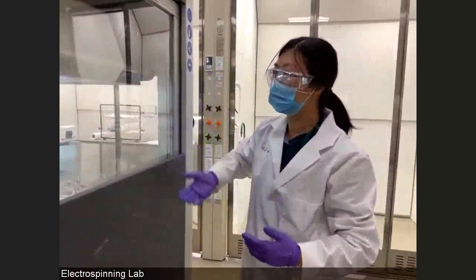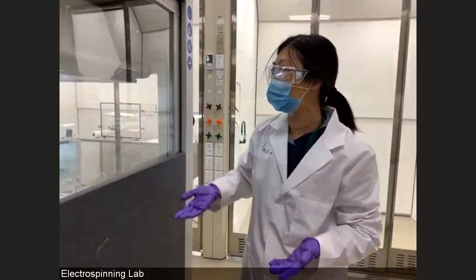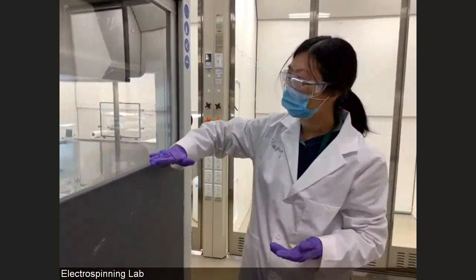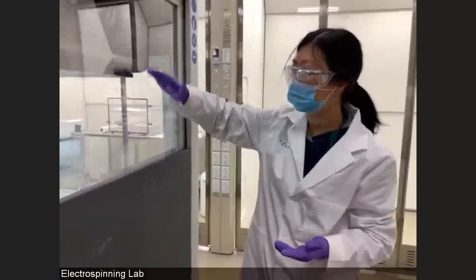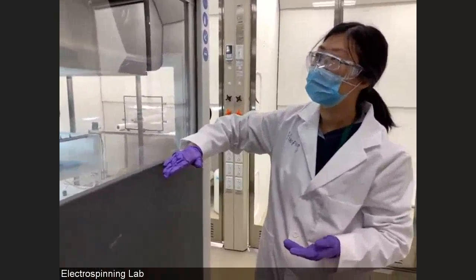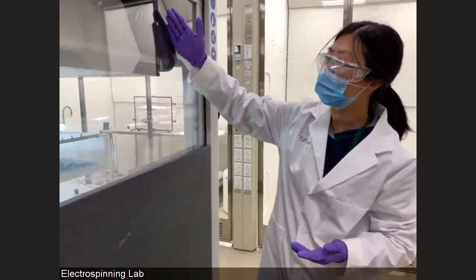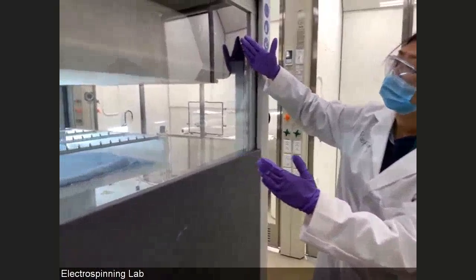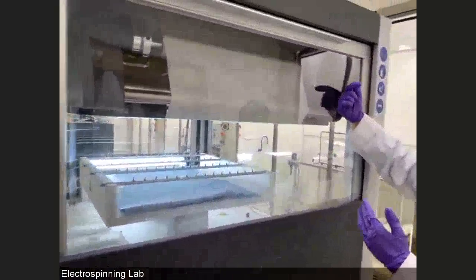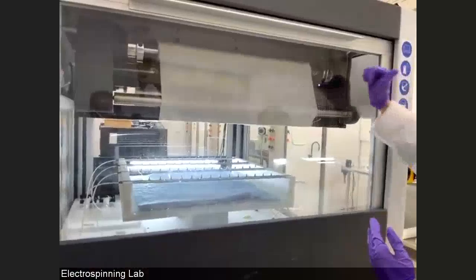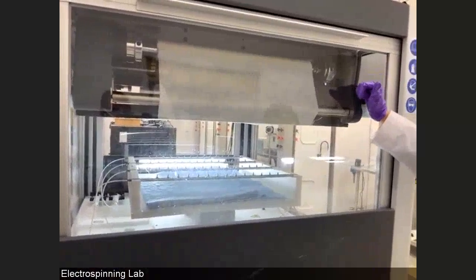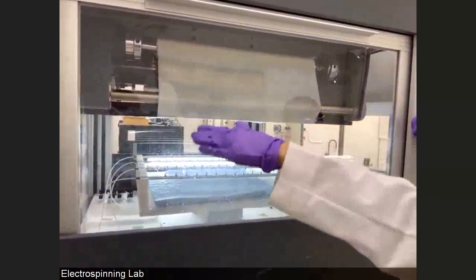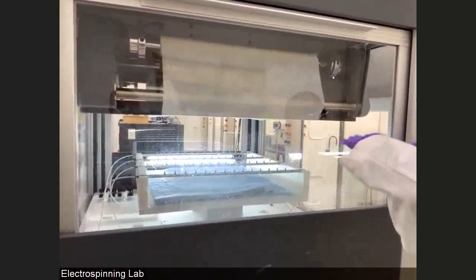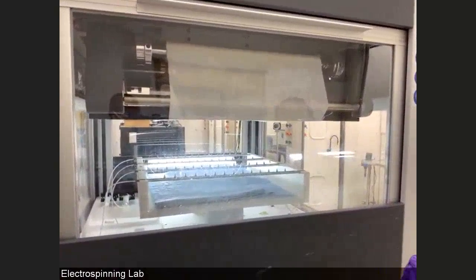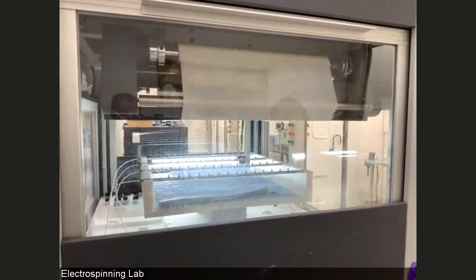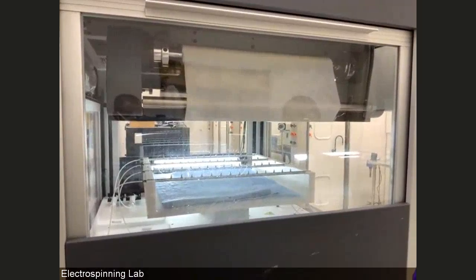We can control all the electrospinning parameters. For example, we can move this plate up and down to adjust the working distance. We can adjust the web moving speed. And you probably notice that in addition to this movement along the y-axis, we actually have a movement along the x-axis in this way. That is what we call a rocking movement, which improves the homogeneity of the deposition over time.